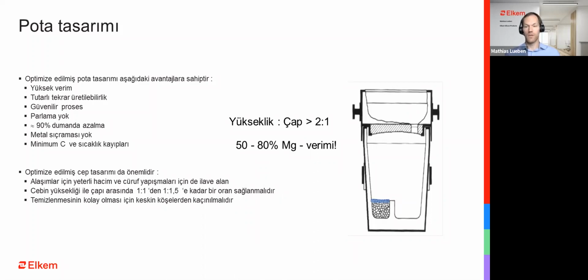Also important is an optimized pocket design. Please think of a sufficient volume for alloys and additional safety space for build-up. A ratio for the pocket of 1:1 or up to 1:1.5 between height and diameter of the pocket is recommended. Important is also a pocket without sharp corners, which is easy to handle to keep it clean.